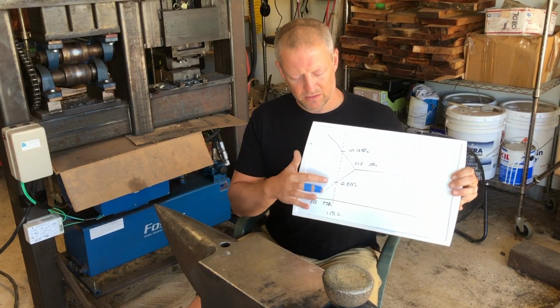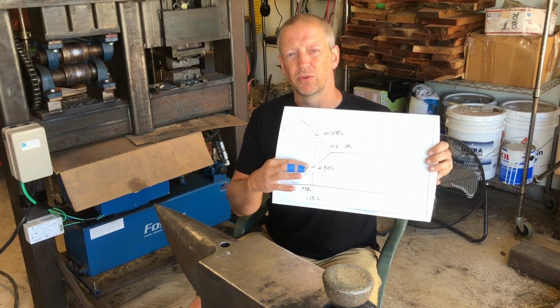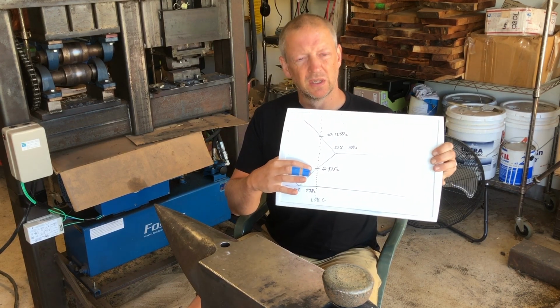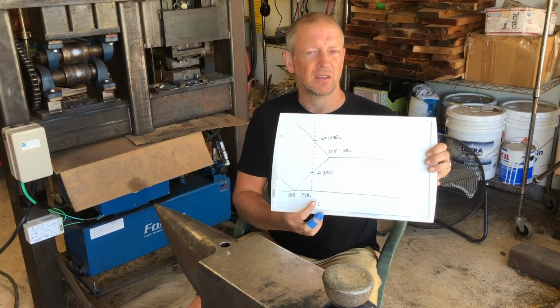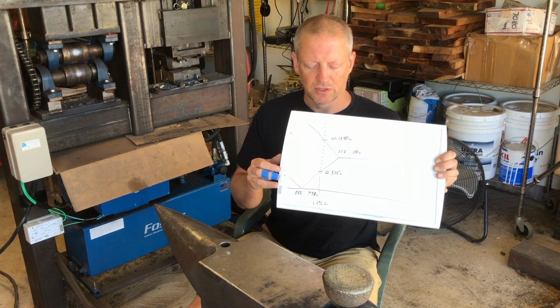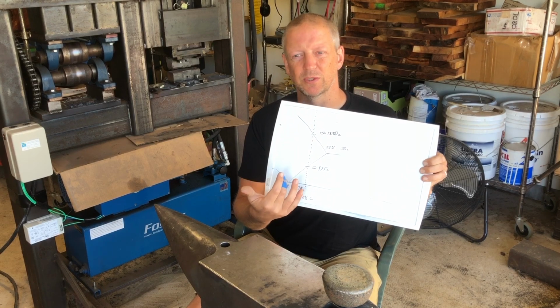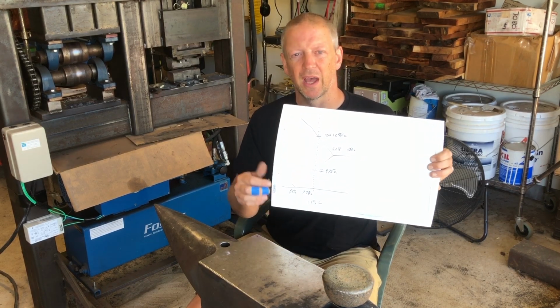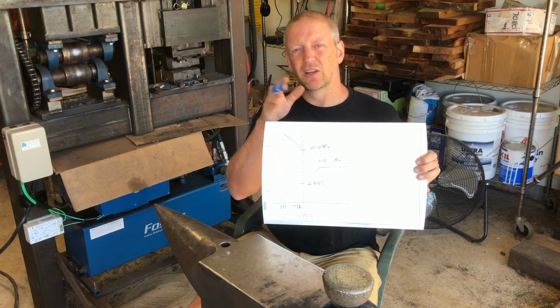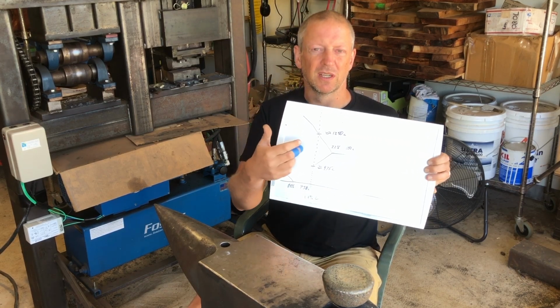Other thing that's going to happen in that process is, we are obviously roasting. If we're at 1250, we are well above the ACM. By the way, this little dotted line is 1.5% carbon, which, obviously some Wootz has more carbon than that, some Wootz has less, but that's a pretty good midline of where historical Wootz fell. Was a little bit above or a little bit below, or a range around 1.5%.